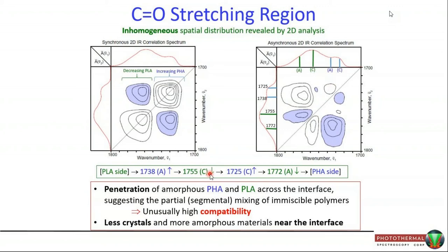followed by the decrease of the crystalline component of PLA, followed by the increase of the crystalline component of PHA, and finally the disappearance of the amorphous part of PLA. So we can actually differentiate the amorphous and crystalline component of the PLA. Likewise, also amorphous and crystalline component of PHA, and we can actually see the spatial distribution of amorphous and crystalline components of PHA and PLA.